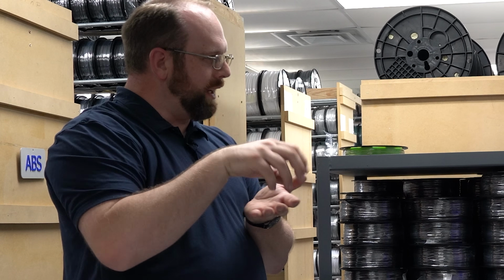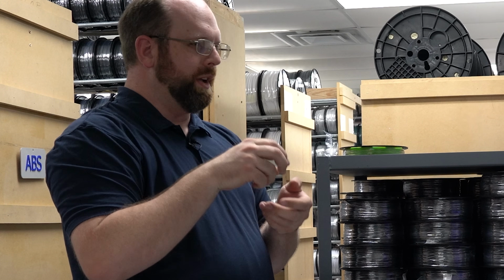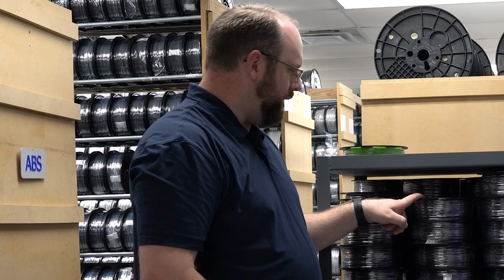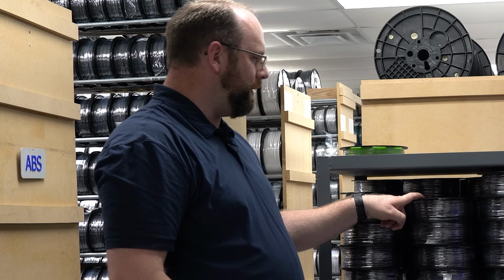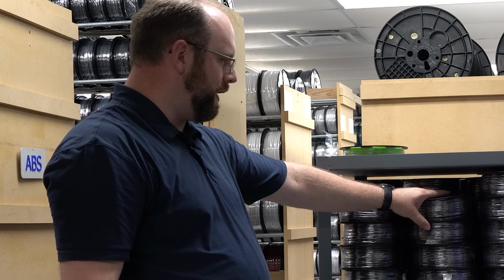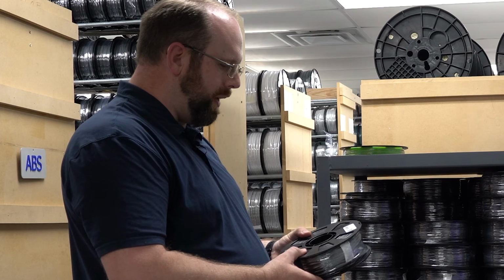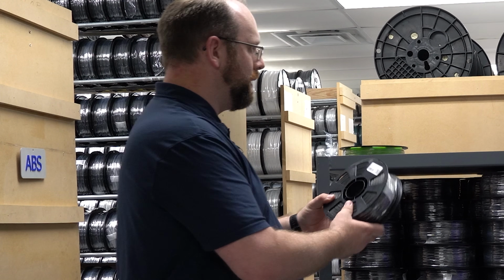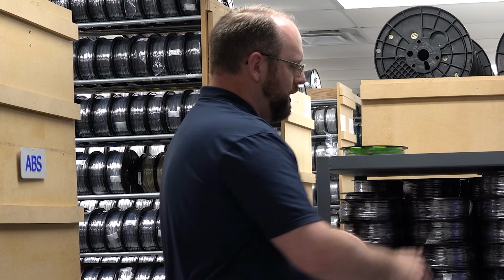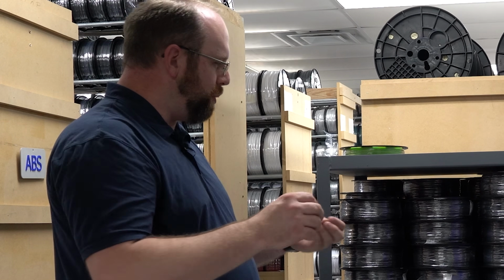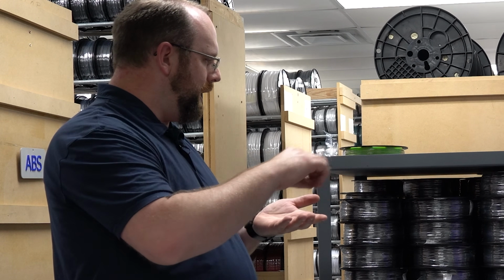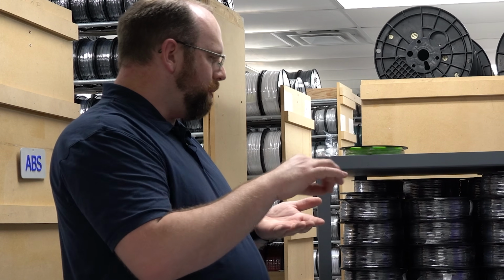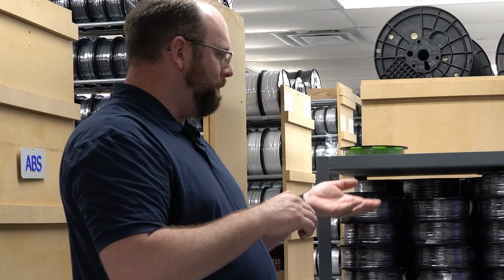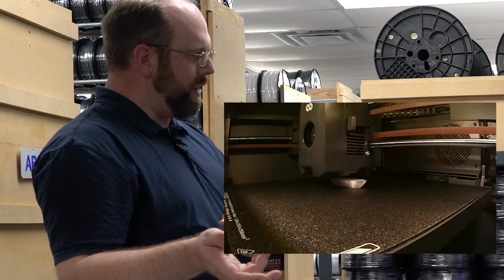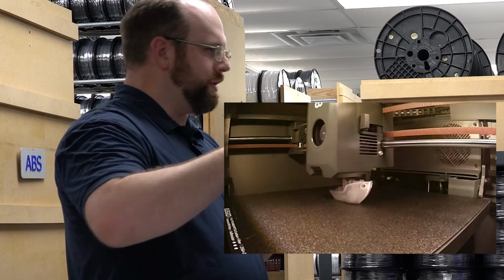So you have this sweet zone of hot and cold to prevent stringing on PETG in particular, because it doesn't flow as well. The melt flow on it is a lot lower for PETG than other materials, and that's why it doesn't want to break, and that's why it's more stringy. But if you get the exact perfect temperature, and that's where maybe annealing is pushing people into that zone, then you'll get rid of the stringing.